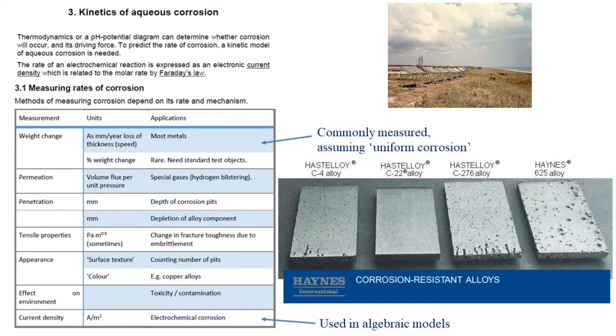But the result is that we get this surface, and the pitting corrosion cannot just be described by a uniform thickness of metal being lost in terms of millimeter per year over the whole surface, because actually none of these metal samples are losing much material uniformly, but some of them do nonetheless have a very serious problem because they are covered in these so-called pits, where the corrosion of the metal by dissolution is concentrated into small areas, and those areas have quite deep holes, which could easily be catastrophic, for example by allowing a pressure vessel or a pipeline to leak.